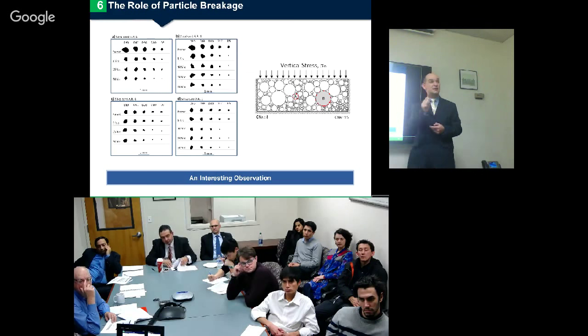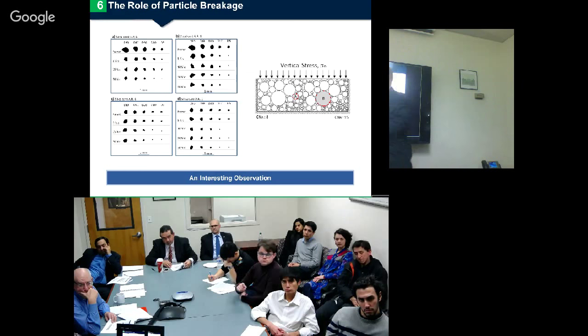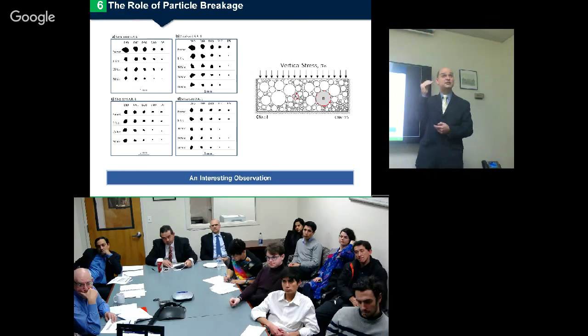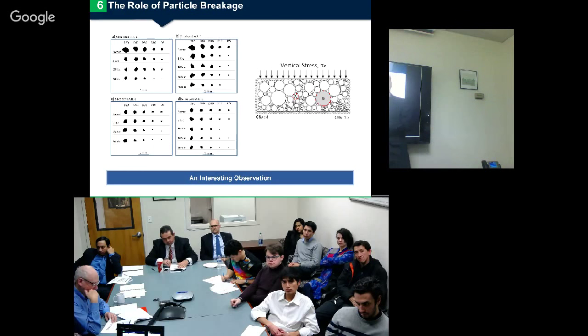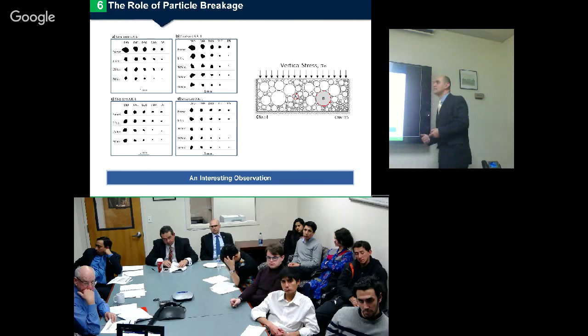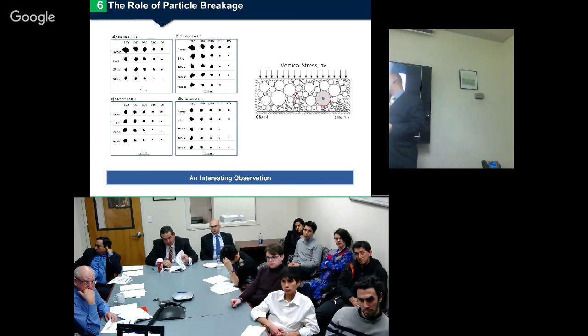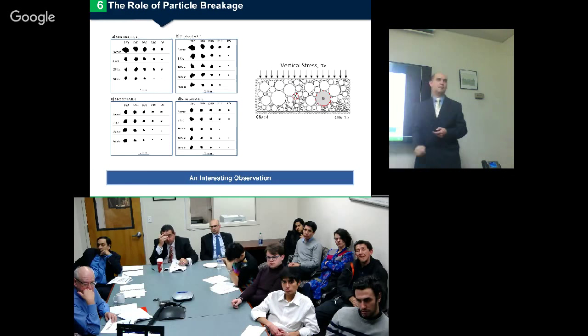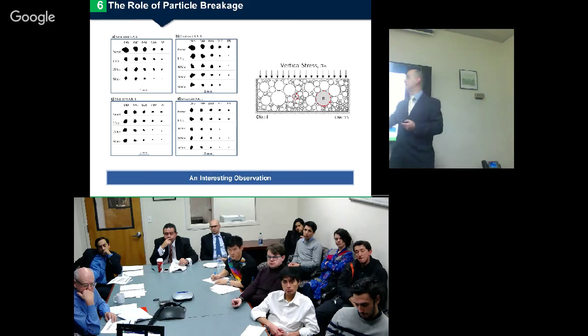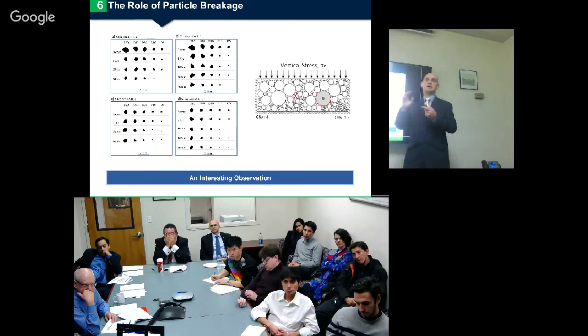By choosing a specific diameter of 90, 60, 30, 10, and 5%, and arrested strain starting from obviously 0 strain, which is the original material, 5, 15, and 30, and here 5, 10, 20, and 30, we will see the evolution of the particle. I have to mention that this particle right here is not the same one as the ones lower. These particles are random particles that carry these similar conditions. That D90 is being identified. The aspect ratio that we saw is identified.